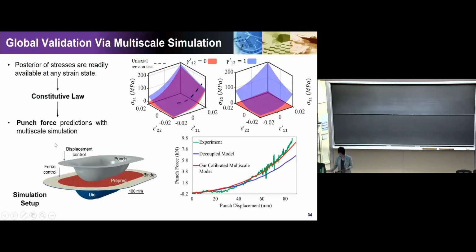So we looked at this. It actually shows the experiment data. It's a green curve, so it's kind of fluctuating. And the decoupled model is what people used in the literature, which does not consider tension and shear coupling. And the red curve is our calibrated multiscale model. So you can see that at the highest scale level, using the corrected, calibrated material behavior, we could actually predict very well the global behavior for the whole part.